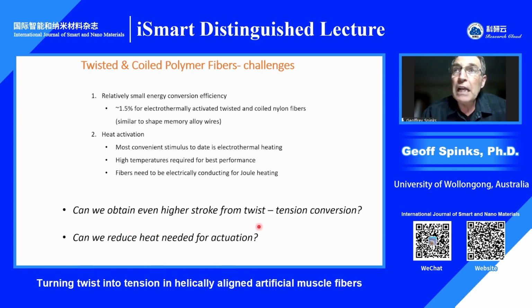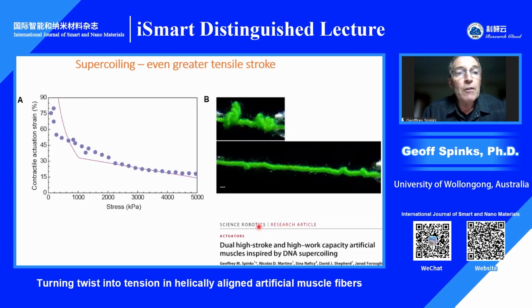How can we improve the energy conversion efficiency by essentially getting more out of these fibers? And secondly, are there materials that operate at lower temperatures inherently? So let's look at the first one. The first one is impacted by a new mechanism called supercoiling. This is something that we've just published a couple of years ago, and it's a way of producing much higher strokes from twisted yarns and fibers.